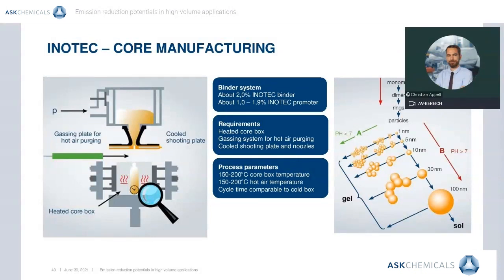The resulting molding mixture is fluidized by compressed air and transported to the cavity of the core box via a cooled shooting plate with integrated shooting nozzles. High diameters of the shooting nozzles and temperature control of the shooting plate are fundamental to assure high productivity in the production and sand cores of high quality. The shooting plate shuttles aside and is simultaneously substituted by the gassing plate.